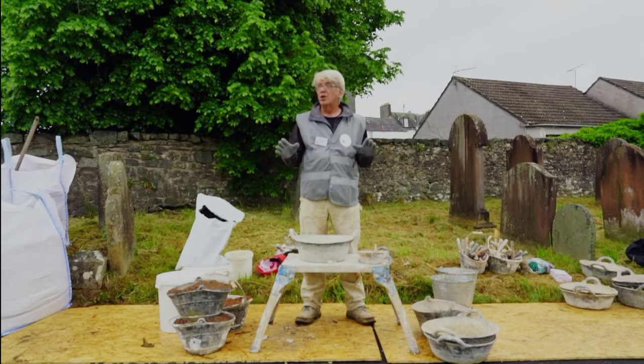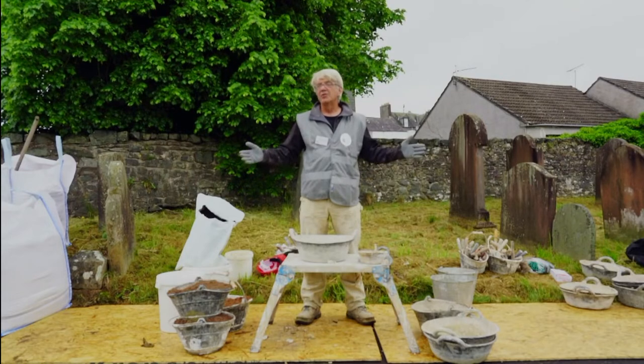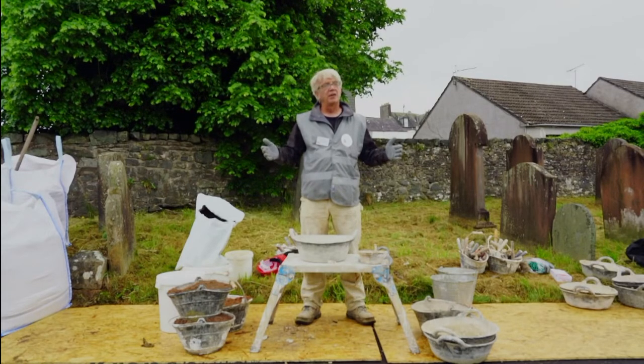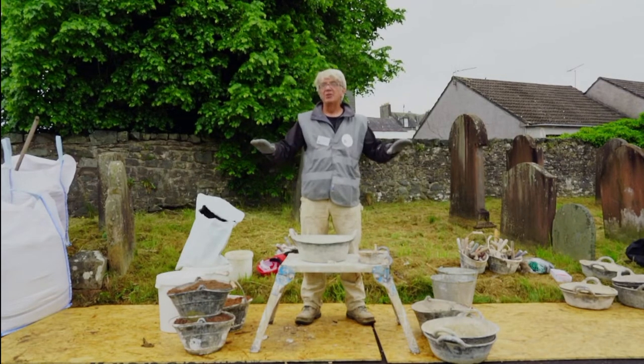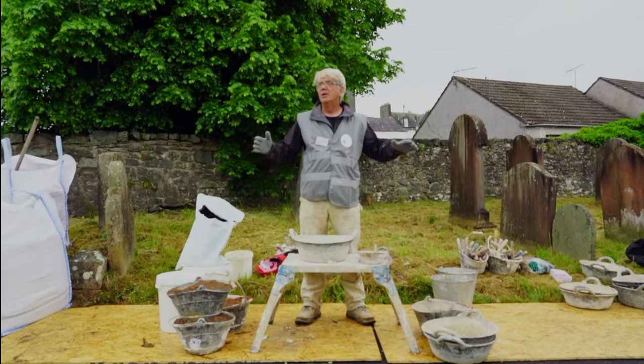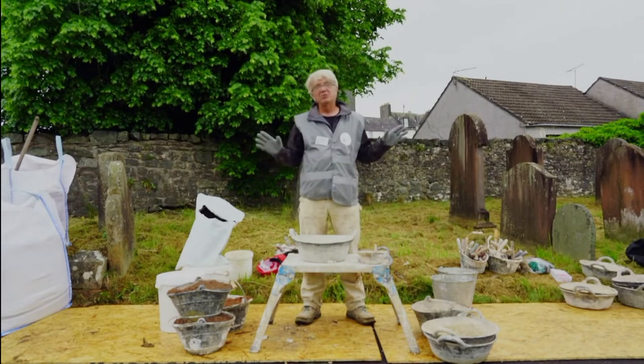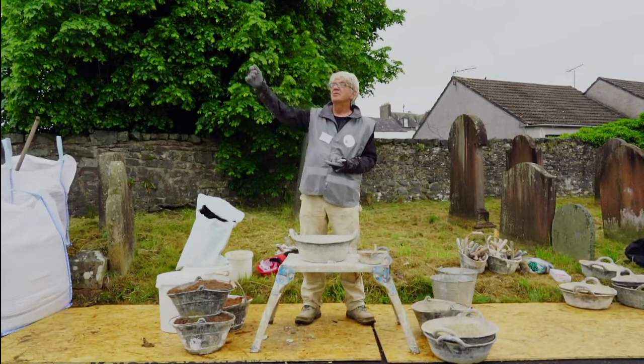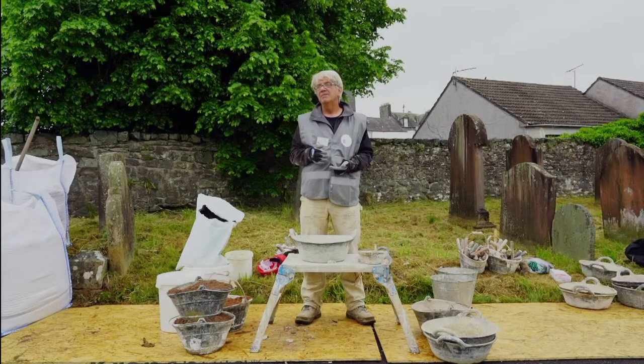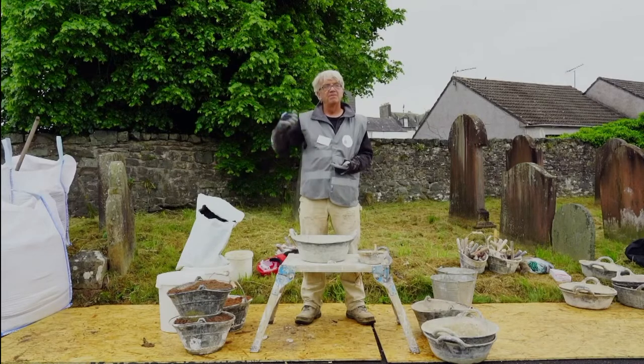And what they certainly would not do, and I'm going to say this here, is what the Scottish Lime Centre and others say you should do, which is to put linseed oil in that lime putty. No. That will make it non-breathable. That will make it waterproof. Why do we want a waterproof mortar? We don't. We want a capillary active mortar. So don't listen to anyone who tells you to put linseed oil in lime wash. You can do it once. You'll never get another coat of lime wash on it. It'll never stick on it. And it will trap moisture behind itself.